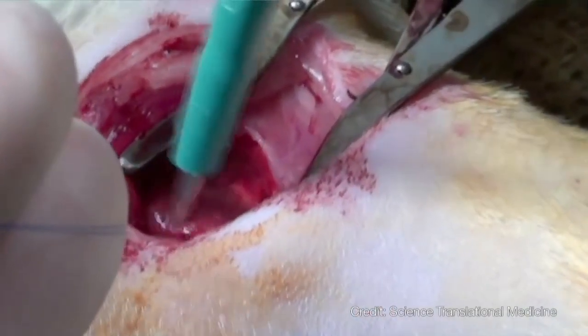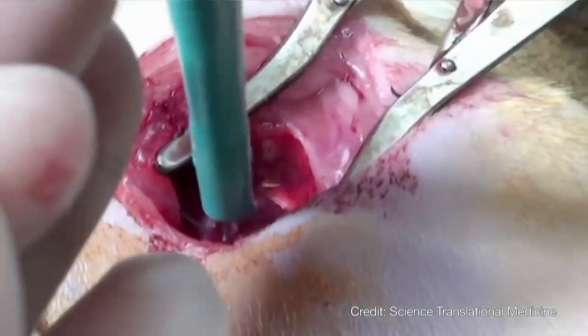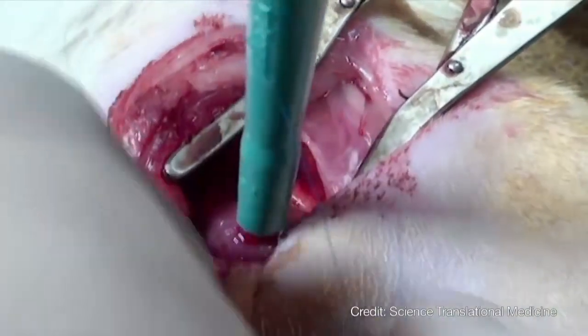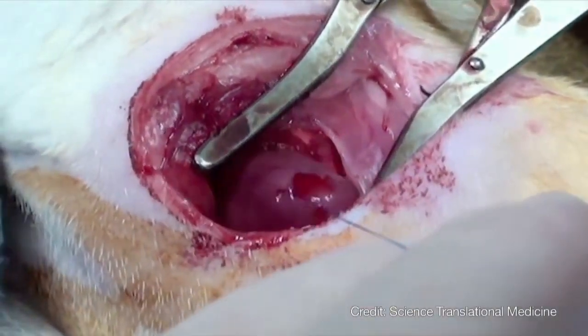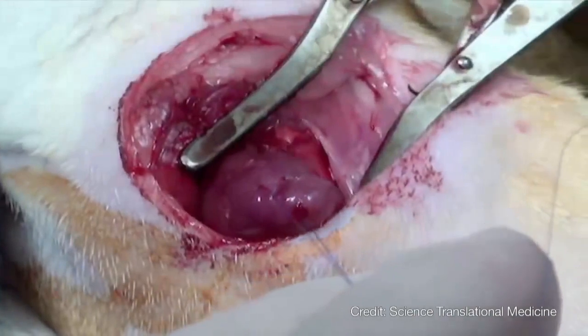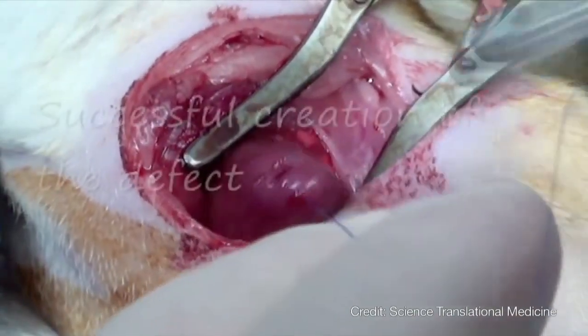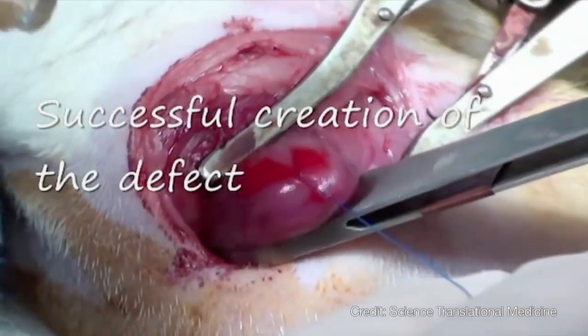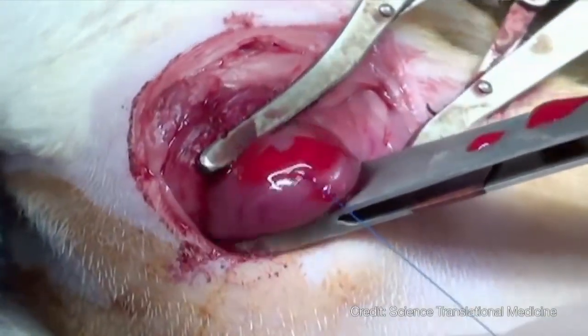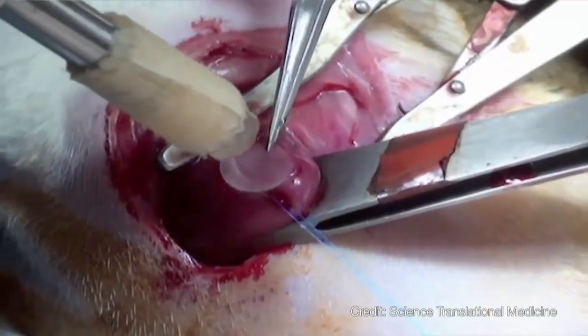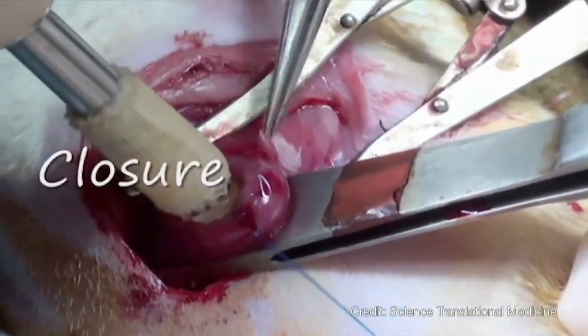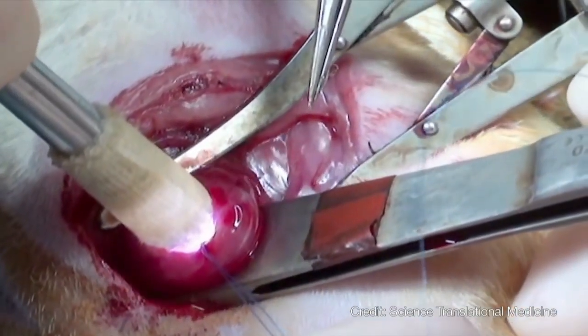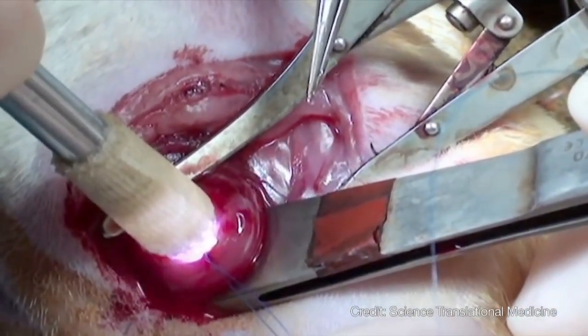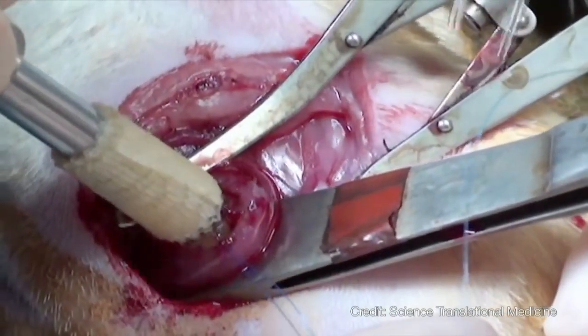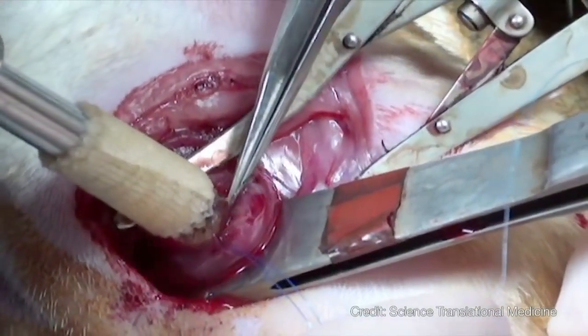Here we make a 2-millimeter defect in a rat heart, and we close it temporarily with a suture. We've actually developed another material, a patch, which is fully degradable and elastic, also transparent. And we coat the glue on the underside of that patch. And you'll see we don't really remove too much of the blood during this procedure. We then apply the patch, the glue is facing the tissue, and we shine light for 5 seconds. But something went horribly wrong. The patch actually slipped away from us, completely unexpected.